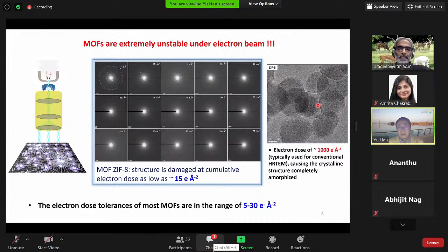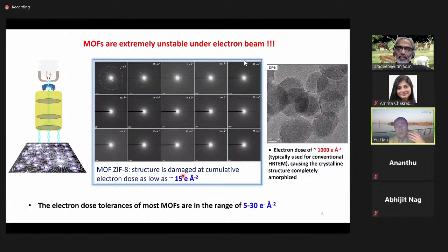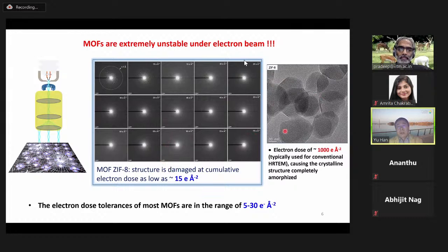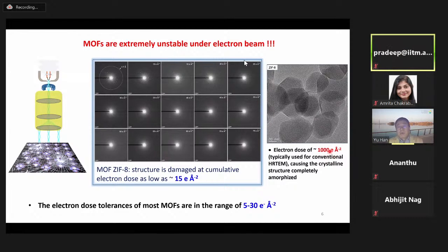Okay, so to quantitatively understand the beam sensitivity of ZIF-8, we conducted electron diffraction experiments to monitor the structure evolution of ZIF-8 under electron beam irradiation. And it turned out that when the cumulative electron dose reached about 15 electrons per square angstrom, the structure damage occurs. So this means if we do want to capture the crystal structure of ZIF-8, we must control the total electron dose below this value. As you can see, this value is about two orders of magnitude lower than the electron dose needed for conventional HRTEM.